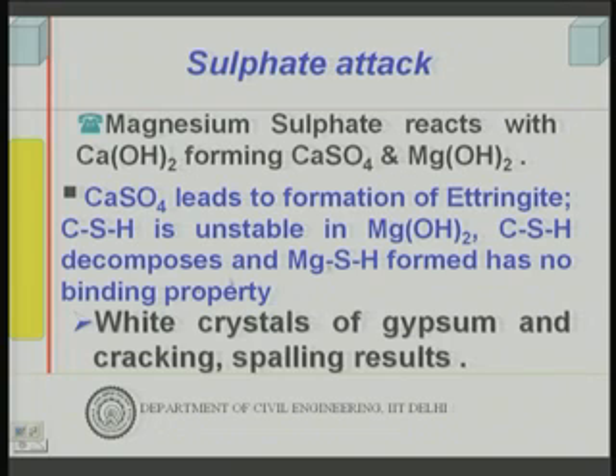So, this CSH tends to decompose in magnesium hydroxide environment, resulting in formation of magnesium silicate hydrate in the long run. So, this is important. This is unstable in magnesium hydroxide environment, and finally this is formed, and this has got no cementing property. So, with cement hydrates in the presence of magnesium hydroxide, not only can ettringite formation take place, but at the same time it can also destroy the CSH structure, therefore the bonding properties of the cement will be lost. So, magnesium sulphate is even more dangerous than others.